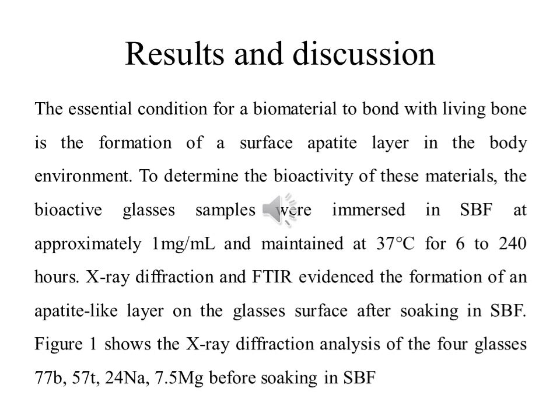The essential condition for a biomaterial to bond with living bone is the formation of a surface apatite layer in the body environment. To determine the bioactivity of these materials, the bioactive glass samples were immersed in SBF at approximately 1 milligram per milliliter and maintained at 37 degrees Celsius for 6 to 240 hours. X-ray diffraction and FTIR evidenced the formation of an apatite-like layer on the glass's surface after soaking in SBF.